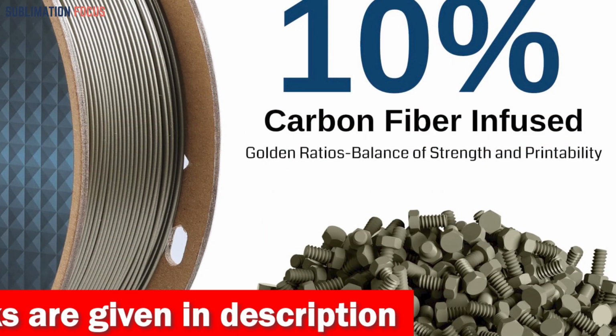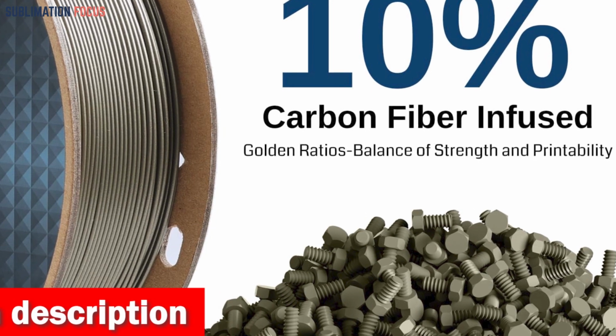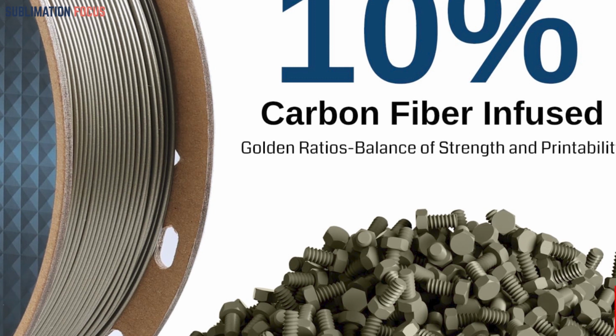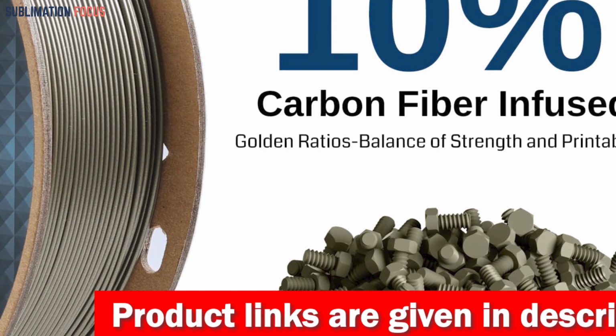extremely hot environments. To achieve optimal results, it is crucial to ensure that the filament is completely dry before printing and to utilize an enclosure for precise temperature control. It is recommended to keep your settings within the temperature range of 220 to 260 degrees Celsius while maintaining a heated bed temperature between 70 to 100 degrees Celsius.